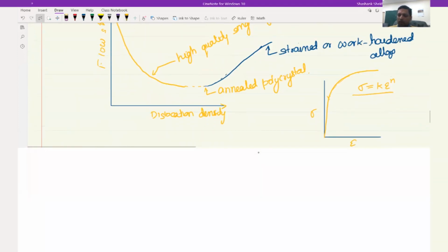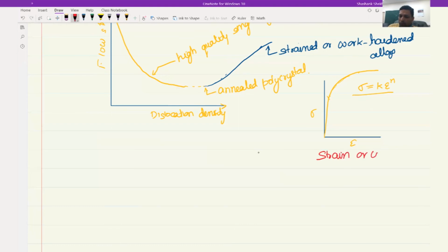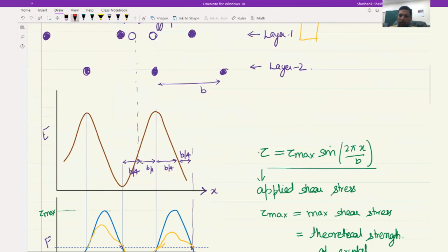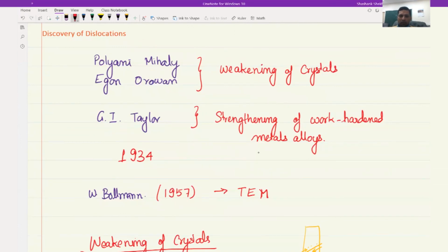So this is what is strain or work hardening, which cannot be explained by our earlier model. So these two things clearly emphasize that there must be some other mechanism for deformation, and hence the two people, Polanyi and Orowan, worked on the theory of dislocation based on the observation that the theoretical strength and experimental strengths do not match. And Taylor saw that when you deform a material, when you do some metal working on it, its strength increases. So again, he hypothesized that there must be something else, and therefore he came up with the concept of what we now call dislocations. So together these three are credited with the theory of dislocations.